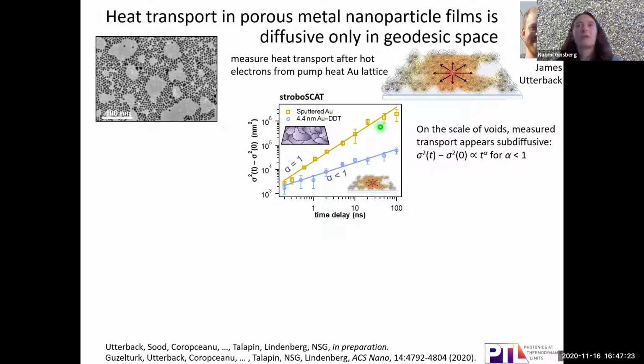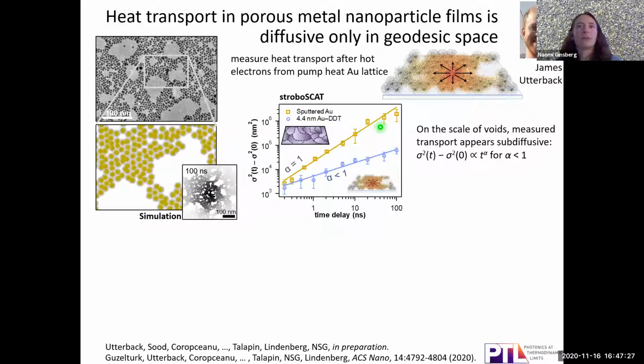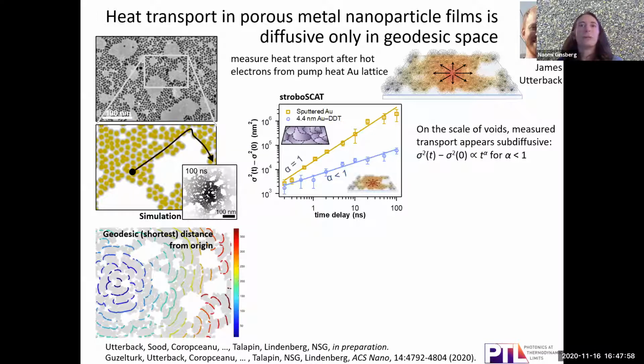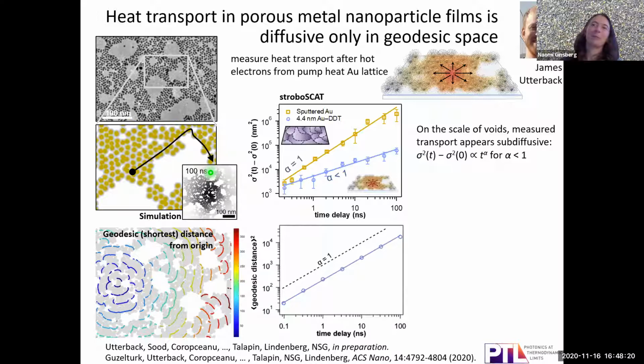So James recapitulated the behavior in simulated heat transport, including three different components. So these slightly disordered gold particles, their ligand shells, which are basically the coating on them that helps to suspend them when they're sitting in a solution, and these voids based on this TEM image. So in order to rationalize the behavior, we learned that the heat transport is essentially diffusive within the boundary conditions or the confinement that's introduced by these voids. And to do so, James realized that he could reframe the transport in terms of the geodesic distance from the origin where the heat was generated. So basically the shortest distance to a point through the actual material. And diffusive behavior is actually nicely recovered if we plot the mean squared geodesic distance as a function of time.